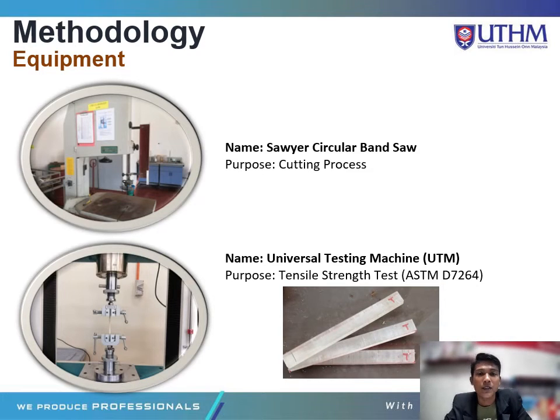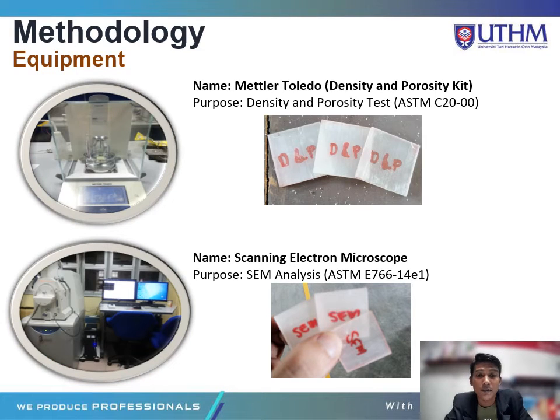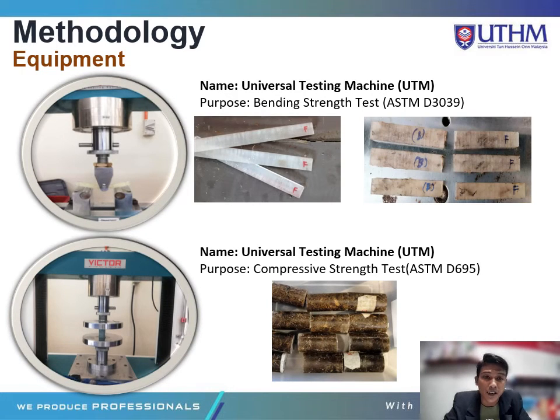And for the equipment, I'm using a Sawyer Circular Band Saw for the sample cutting process. For the tensile strength test, I'm using a universal testing machine, using the standard ASTM D7264. For the density and porosity test, I'm using a metal density and porosity kit, using ASTM C20-00. For SEM analysis, I'm using a scanning electron microscope. For the bending strength test, I'm using a universal testing machine, using ASTM D3039 standards.